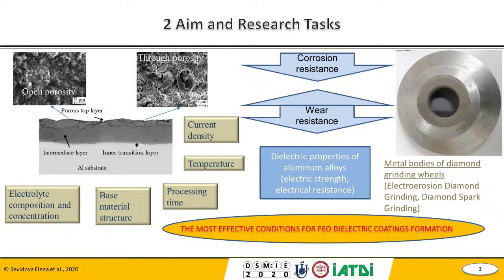And as you can see on the right side, these are typical metal bodies of diamond grinding wheels with PEO coatings in the middle. And for us, the aim of our research was how to make such coatings more viable, more dielectric. Where can we find the most effective conditions? Because we have a large number of different influencing factors, for example, electrolyte composition and concentration, base material structure, processing time, temperature, current density, and others.